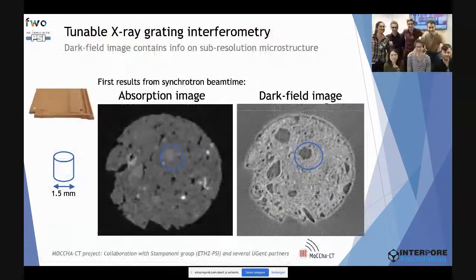So we tested this tunable grating interferometry at the synchrotron, and here you see what it could potentially give you. On the left you see an absorption image, where you see zones which clearly contain big pores, but then you have zones where you cannot say a lot. If you look at the dark field image, you see distinct zones, the more black ones, which contain less signal, indicating that there you do not have pores of a certain pore size below the resolution of the system. So you can obtain information below the resolution of the system by using those gratings.